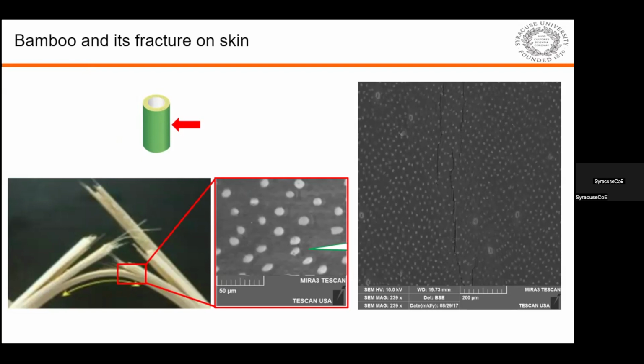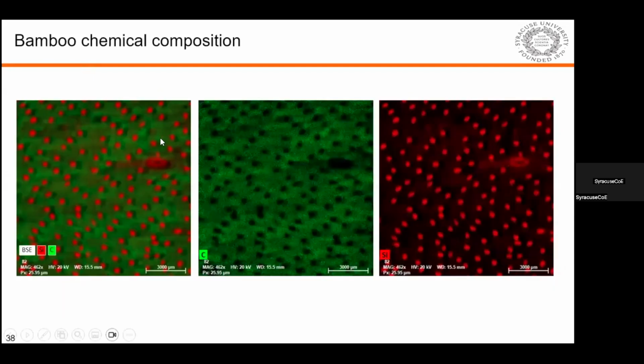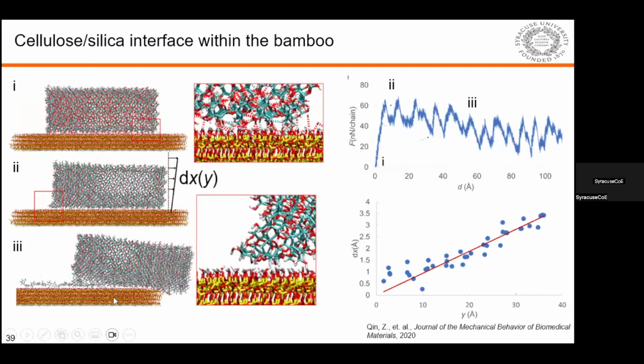And here in the microscope, we see that once there's a mechanical fracture, the crack will not penetrate through those silica particles, but will tend to wind around the silica particle. That suggests this is good for higher energy release, because that creates a much longer pathway once the material needs to fail. And here is a back scattering image showing those silica particles are really rich in silicon instead of carbon.